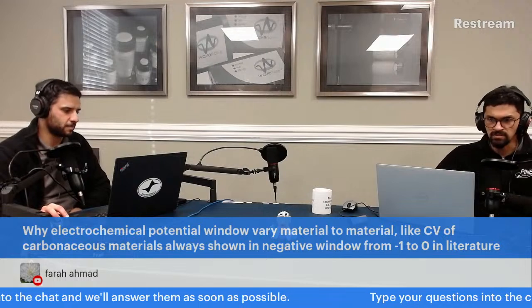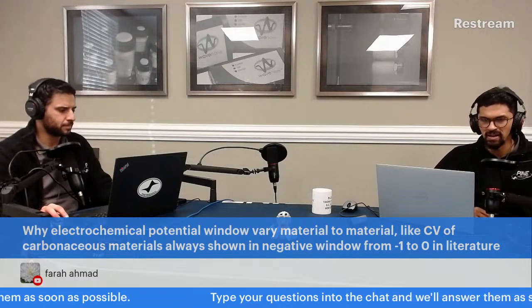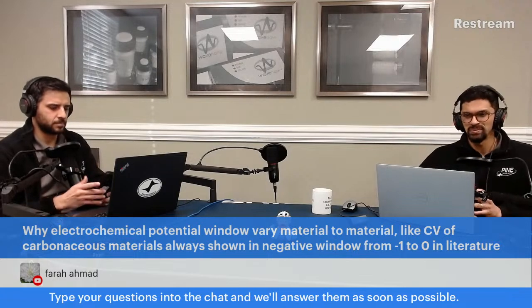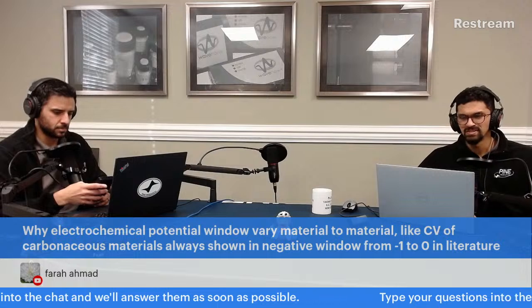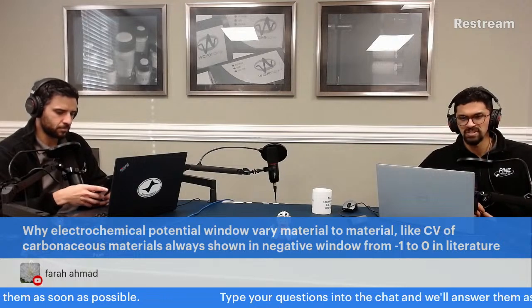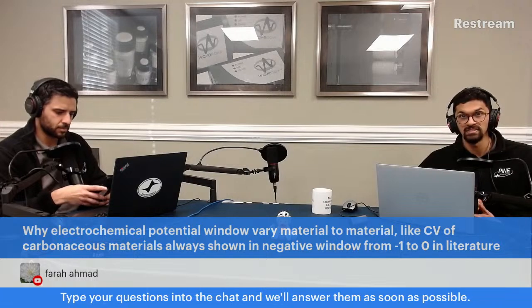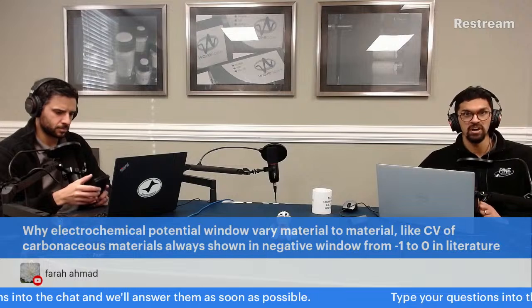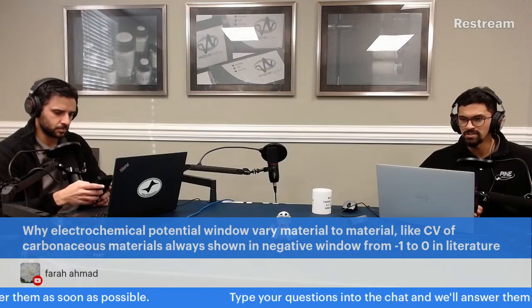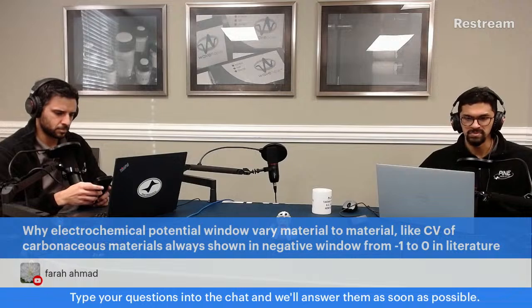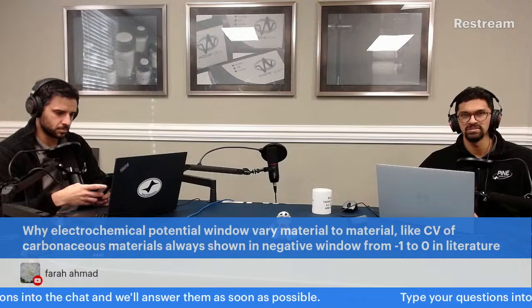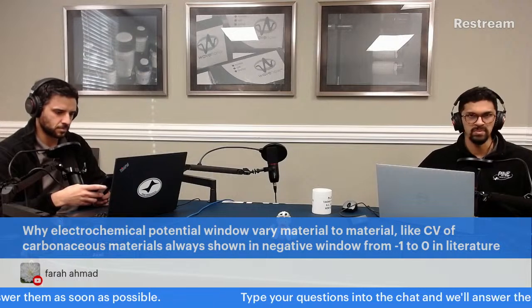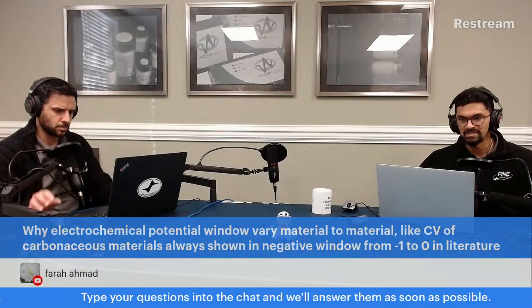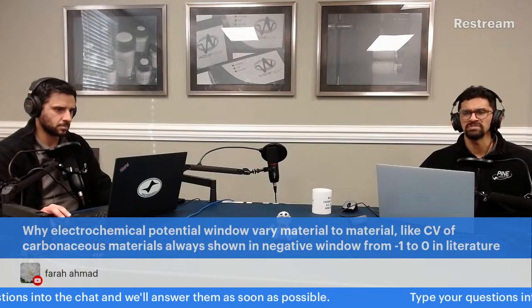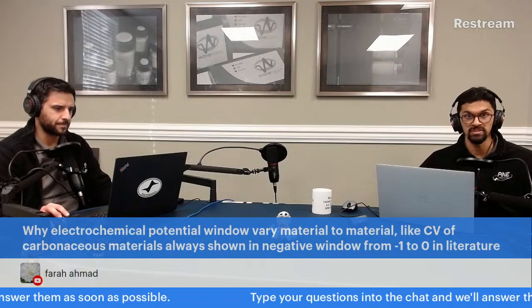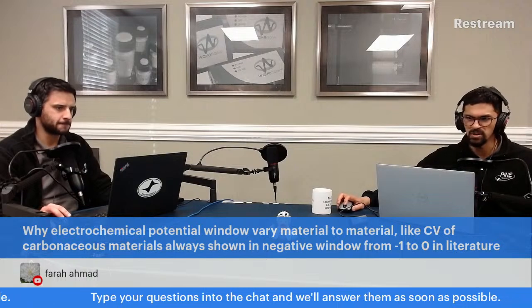Do you have anything to add? Potential windows are always governed by all the stuff that's there: the working electrode material, the solvent. If you have copper as your electrode material, you're going to form copper oxide naturally, without even applying a potential. Copper just naturally starts to oxidize with water and oxygen. So the potential window is always limited by the material because of the other potential electrochemical reactions that can occur. That's both working, counter, and reference electrodes to a small degree, and then the supporting electrolyte and the solvent. So I hope that answers the question.